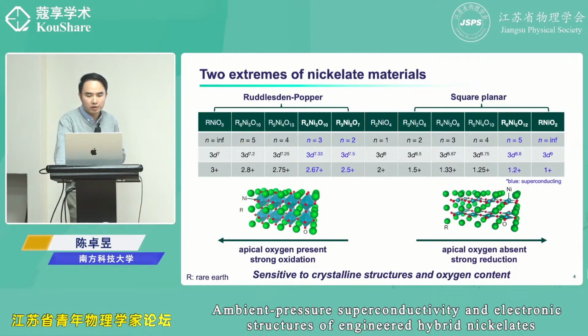The nickelates were discovered so late if you compare with the cuprates or even the iron-based ones. Actually, the idea to find superconductivity in nickelates dates back decades. But only very recently did we achieve superconductivity in this type of material, mainly because this type of material is notoriously difficult to handle. The two extremes, the square planar type and the Ruddlesden-Popper type, are two extremes in terms of oxidation. The square planar needs a very strong reduction to remove all the apical oxygen to get superconductivity. And for the Ruddlesden-Popper, you need to put all the apical oxygen back into the lattice to make it superconducting.